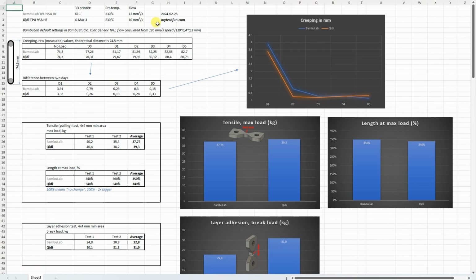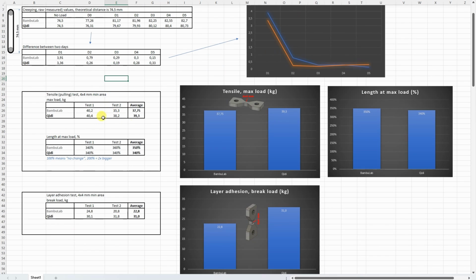And it's time to summarize the results, and this Excel table you can download from mytechfun.com website, but the data also goes to that summary table for my Patreon supporters. Here you can see some print settings, but let's start with the creeping. Even here I can see more deformation on BambuLab filament compared to the Qidi, but this is about creeping, so the difference between 2 days can be seen on this table or on this graph. And we can see that basically after the second day it stopped deforming, and after this the results were similar. On the tensile or pulling test, there is no big difference here, and this is the prolongation, actually the new length before the break, and it was also very similar.